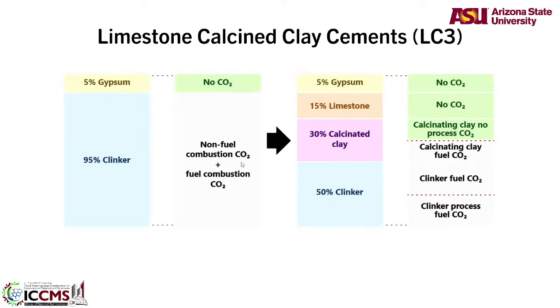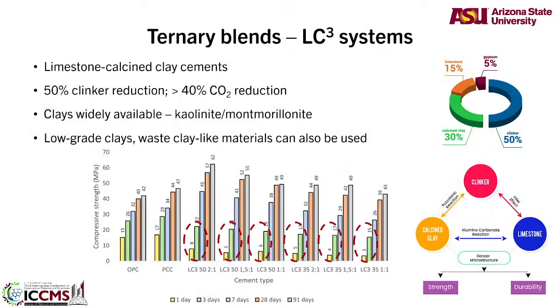So this is your typical Portland cement, and this is your calcined clay. So when you get to here, you have no CO2 from gypsum, no CO2 from limestone, a little bit of CO2 from calcining the clay, but you save a lot of clinker, so you save all of these, and there's lots of CO2 saved as compared to OPC. So that's the idea, that's a strategy. So ternary blends with LC3 systems, one of the biggest problems with such cements is very low early age strength. So 1 day, 3 days, you get very low strengths if you don't play around with it. So the strategy that we are looking at, and some of the new stuff, is how do we do it?